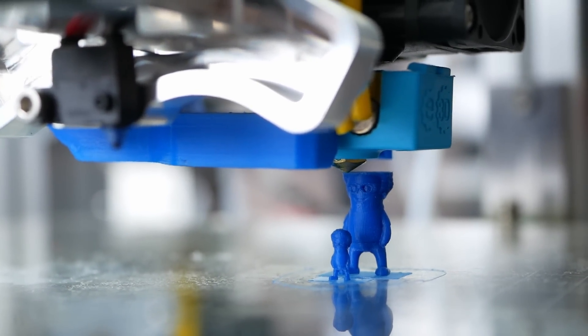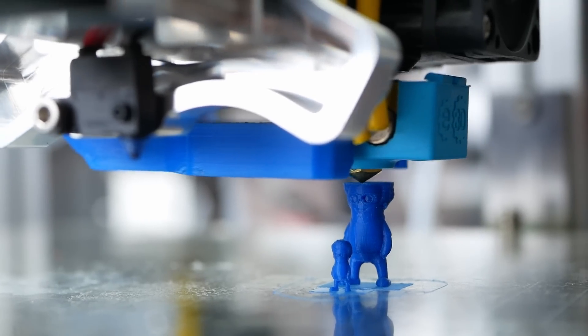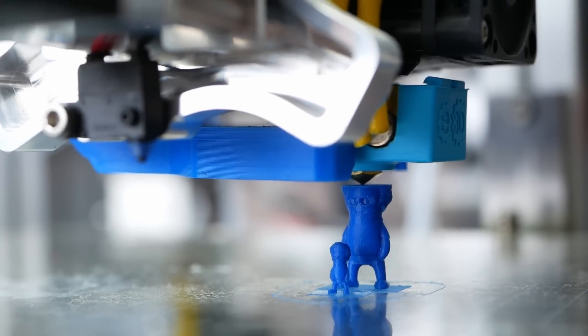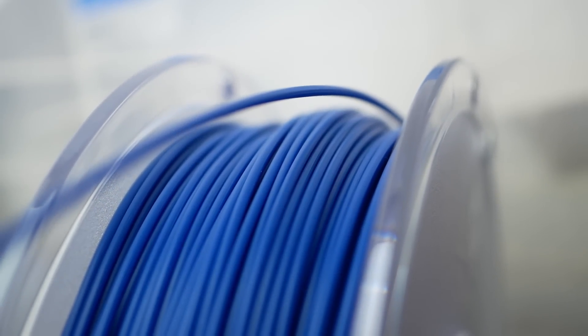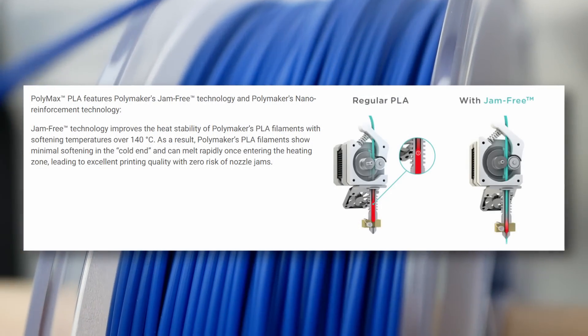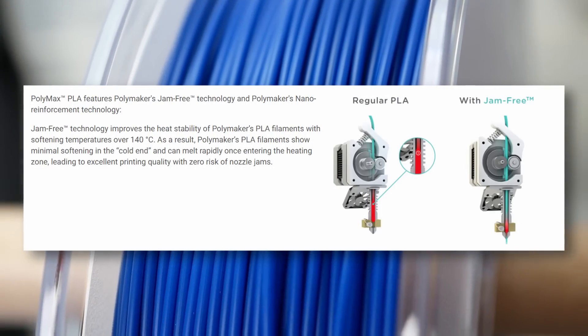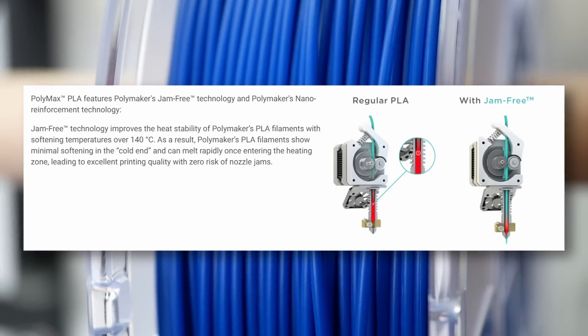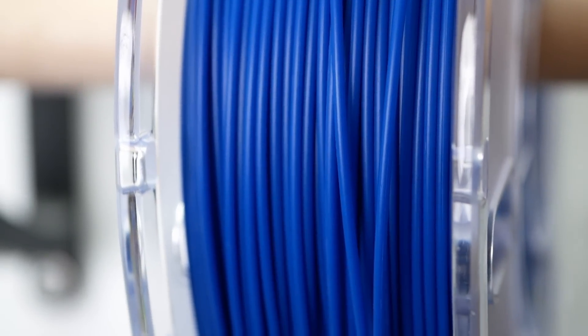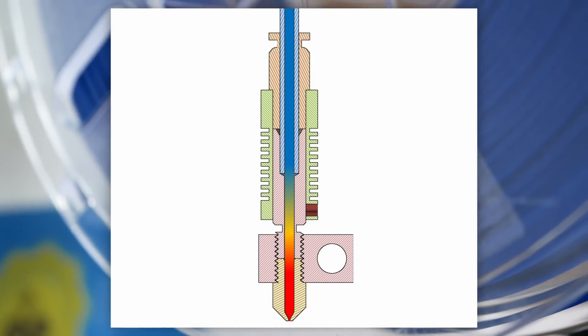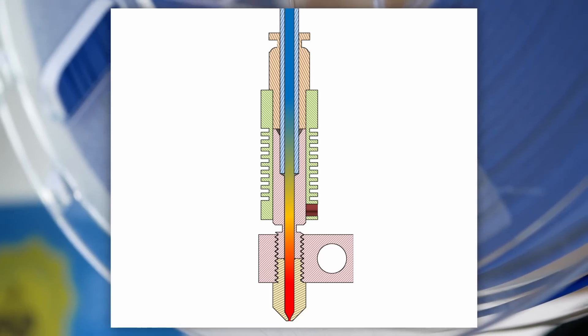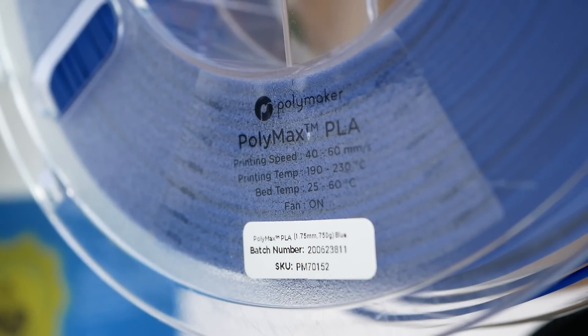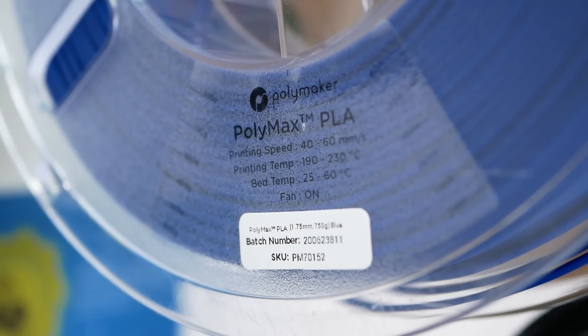If a polymer can't handle that, it will clog the orifice or significantly alter its properties. ABS, for example, has that tendency and materials like PVA can crystallize and basically turn into sand. Maybe one of the even more important things is Polymaker's jam-free technology, where they somehow anneal the filament on the spool to increase the softening temperature. Plastics are a bad conductor of heat. But because the material is so slowly fed using these small nozzles, the heat will travel through the filament upwards, softening it and therefore potentially jamming the hotend. I didn't have a single case of heat creep during the almost 200 hours of test printing.